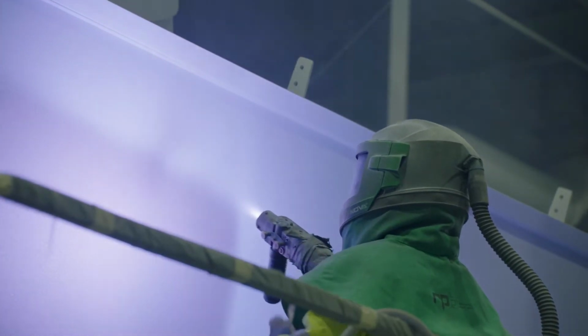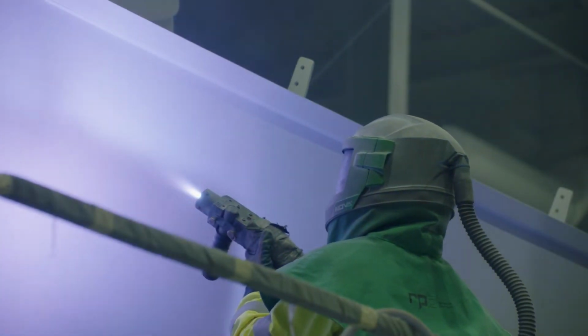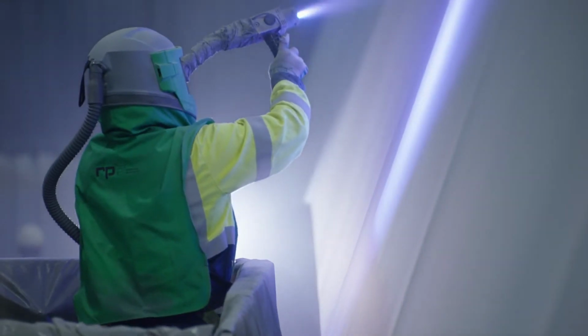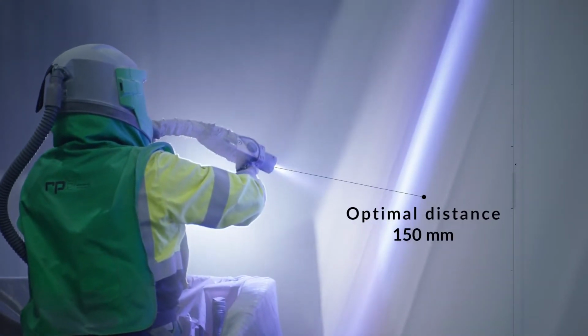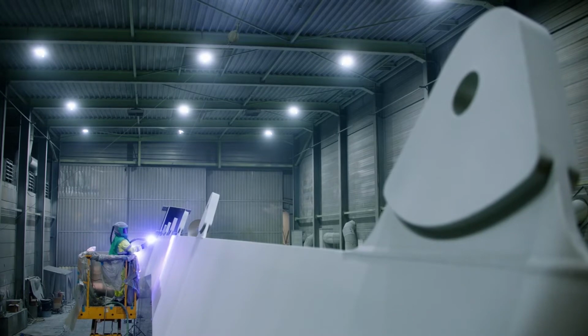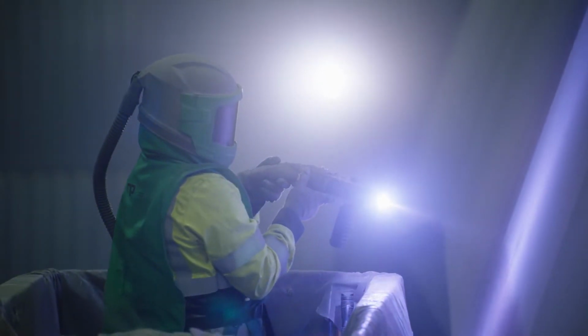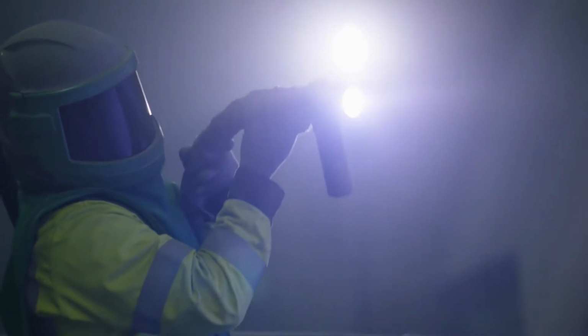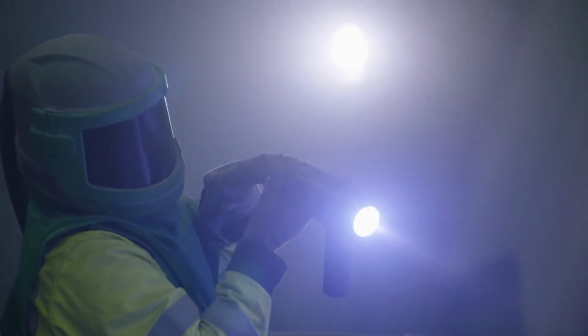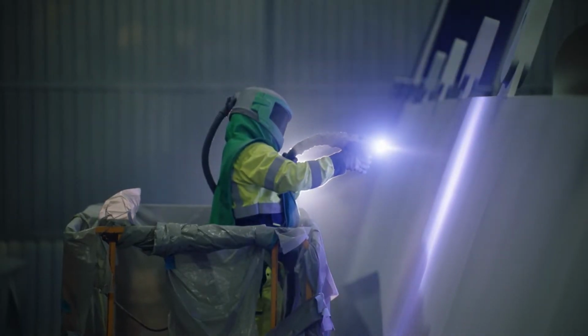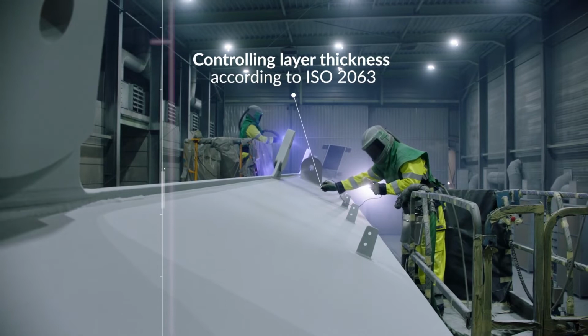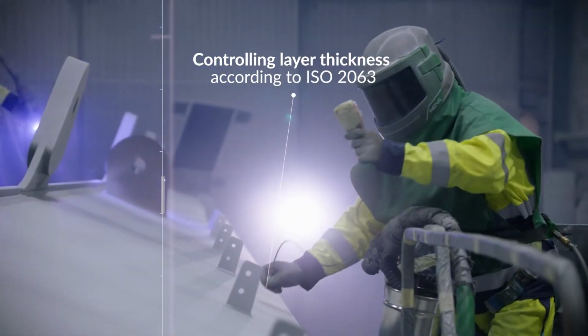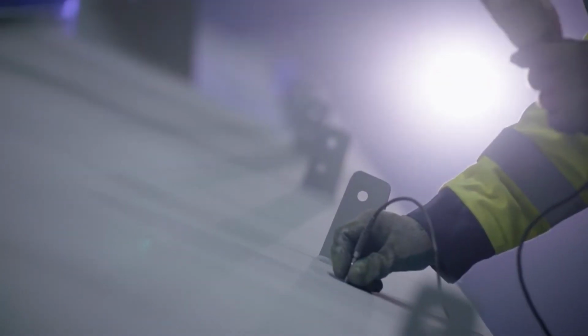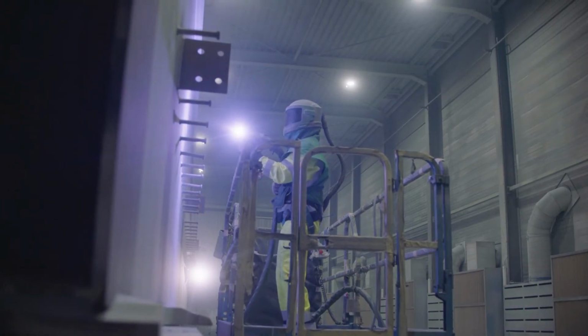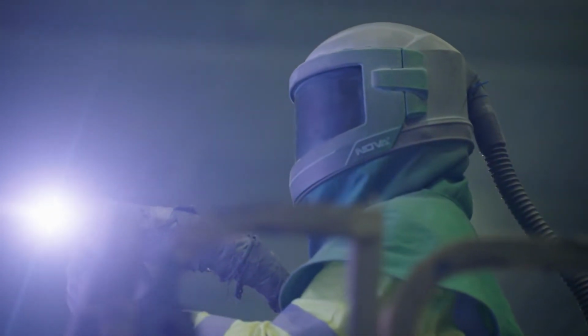The operator should be able to easily reach every area with his blasting or thermal spraying gun. For optimal results, it is important to keep a distance of around 150 millimeters between the gun and the surface. To build the necessary coating thickness, the operator applies several layers of zinc by making multiple passes with the application gun. During the application, the operator measures the thickness of each layer. Depending on the specification requirements, there are several application ranges with varying minimum and maximum thickness. If necessary, the steps have to be repeated until the required final thickness is achieved.